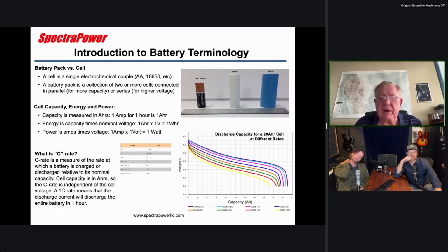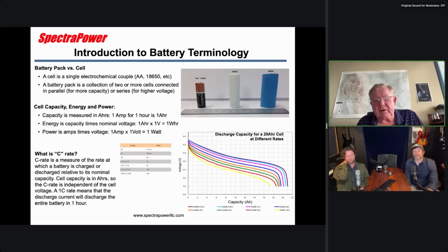But you can see how, as a cell discharges, the voltage drops instantaneously to about 4.1, and then just as it discharges goes down to about 2.8 to 3 volts, which is about the lowest you'll get any energy out of it. So the nominal voltage, which you'll see referred to on battery packs when you buy products, is typically about 3.6. It's sort of the midpoint voltage in the cell's discharge.